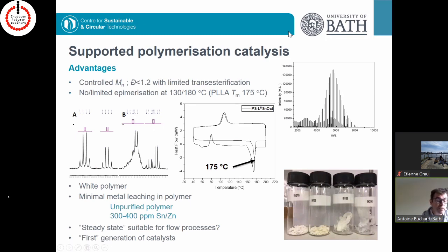Well, the first thing I need to say is that I would qualify this as the first generation of this catalyst. This is not something that's been well explored at all, and I think there's a lot of scope for improvement. And even now with this quite imperfect, almost serendipitous catalyst ligand system, we already have a lot of advantages compared to other systems. So it's quite controlled. We've shown that the molecular weight is as expected. We've got good dispersities, limited transesterification, that we've confirmed by MALDI.